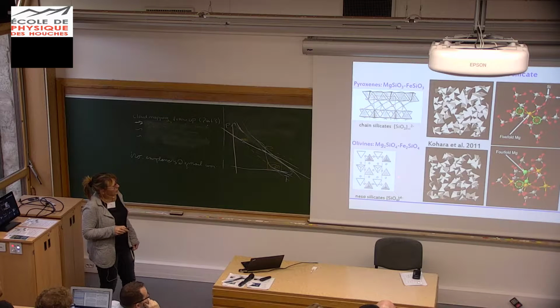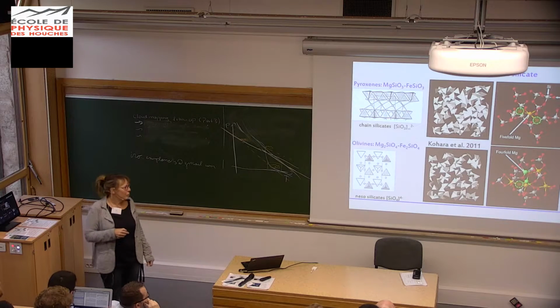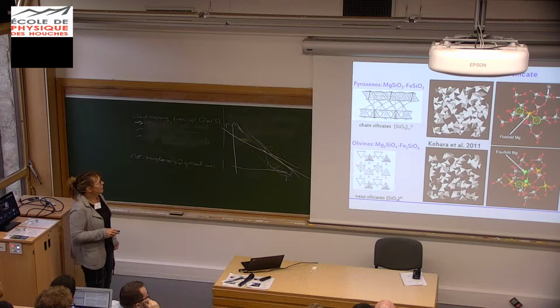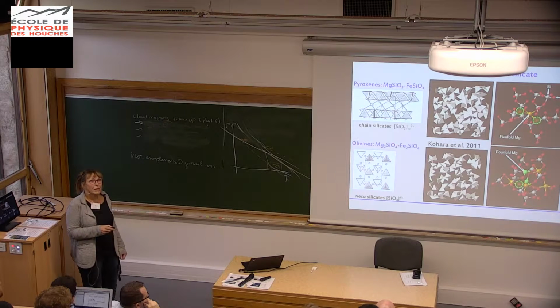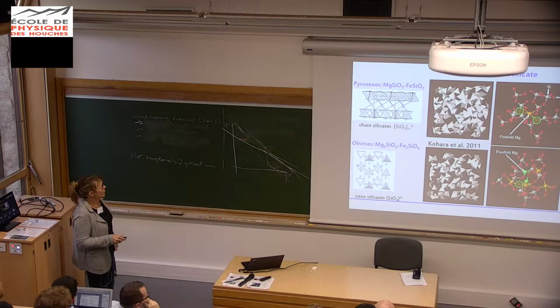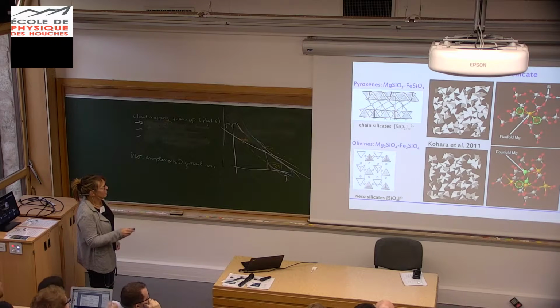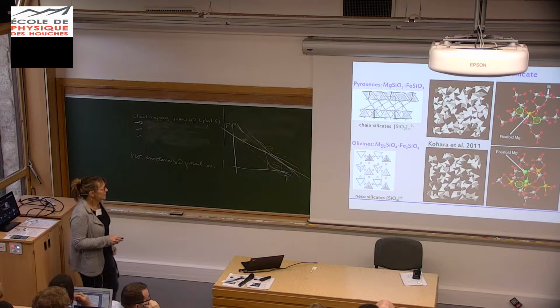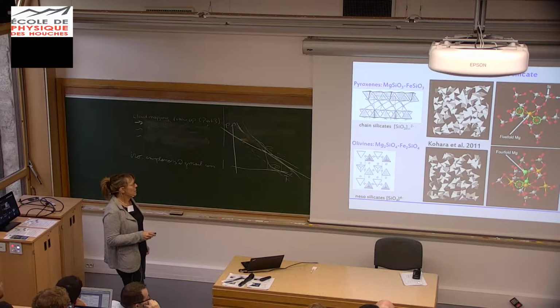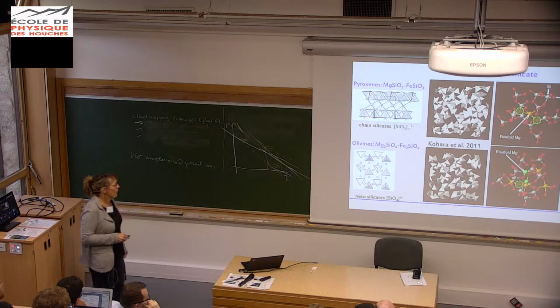Olivine is again characterized by SiO4 tetrahedra, but due to the stoichiometry, we cannot have oxygen bridges between the tetrahedra, so they are isolated, and in between we have the magnesium or iron.